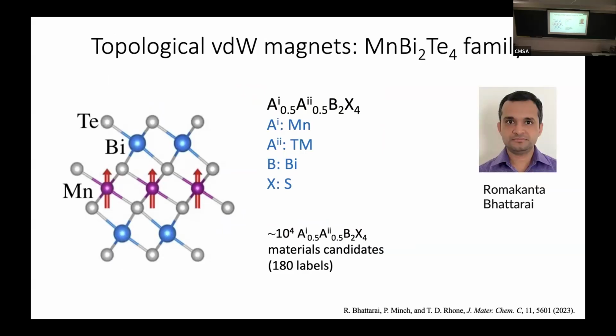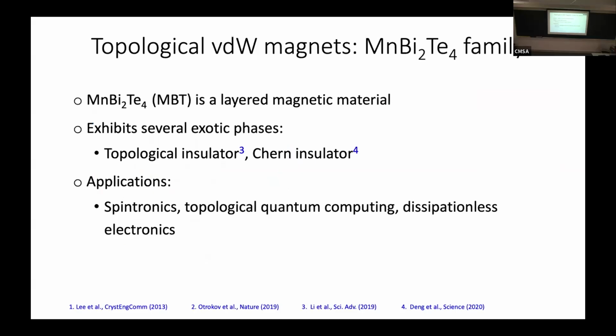He took this manganese bismuth telluride crystal. Manganese atoms are here. Bismuth atoms are here. Tellurium here, here, here, and here. And he would decorate the manganese bismuth telluride with different atoms, different transition metals, like tin and antimony for the B sites, different chalcogens for the X sites. If you do that, you get about 10 to the 4 possible candidates. He chose only 180 to do DFT calculations on, and did a similar thing where he would create a data set, build a descriptor space, build an AI model, and predict the rest of the space using this AI model trained on only a couple hundred data points.